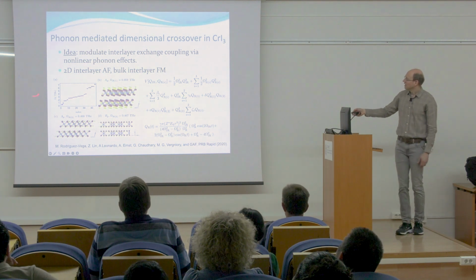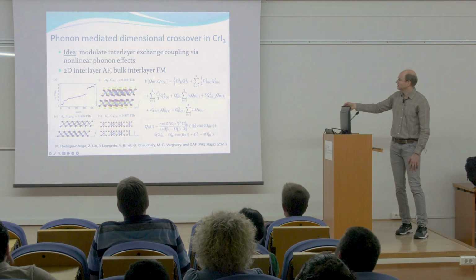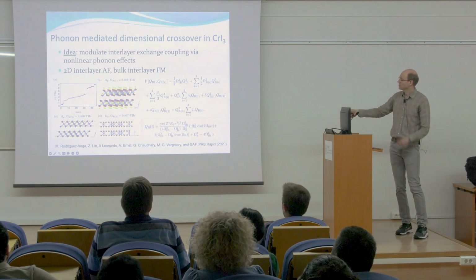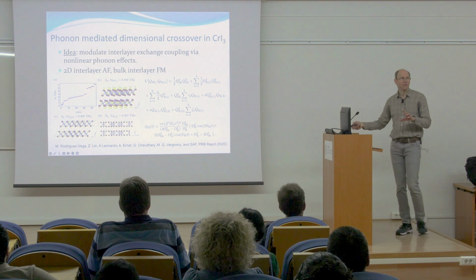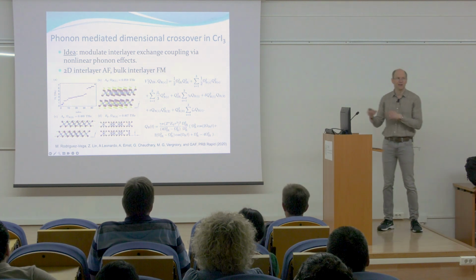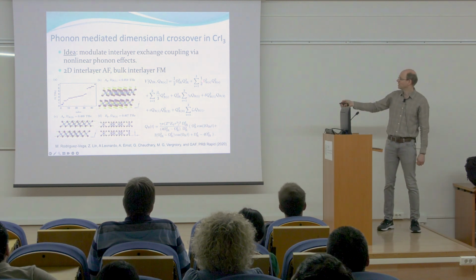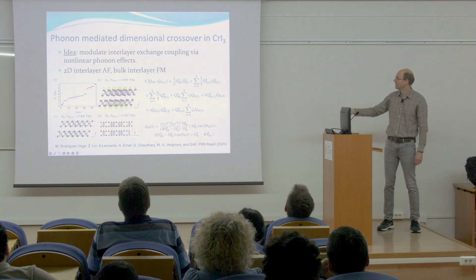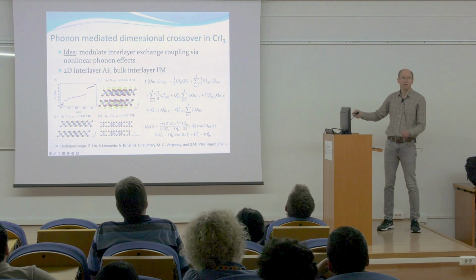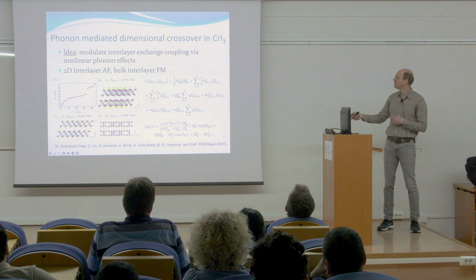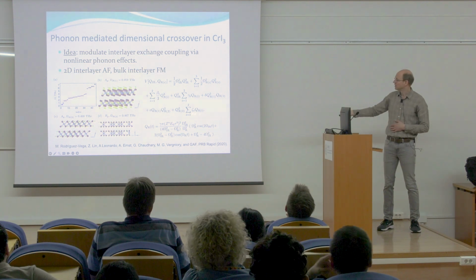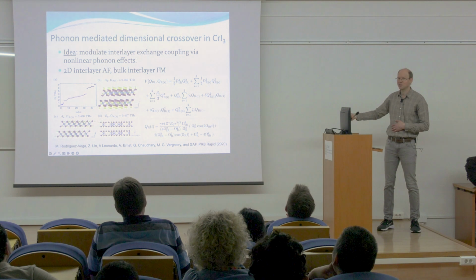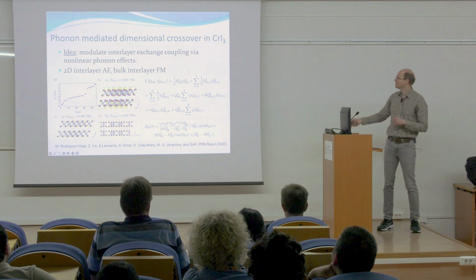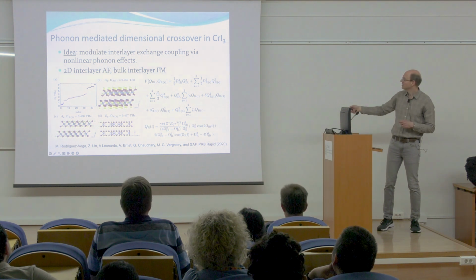Since I'm out of time, I'll just summarize what we did. It's a two-step process. The first step is that we do a symmetry analysis of the vibrational modes of the crystal. We write down the allowed terms of the potential between these IR and Raman modes based on symmetry. Then we ask first principles experts, such as Aritz, to calculate the coefficients of these.